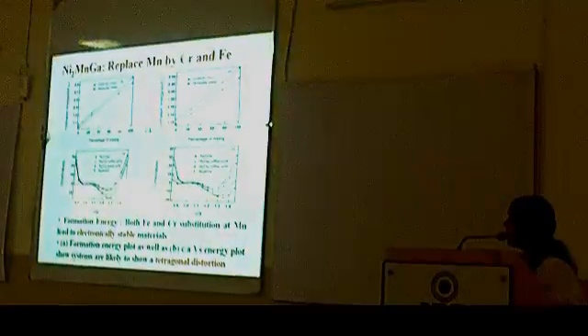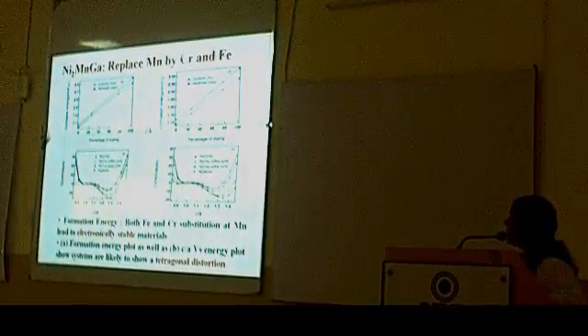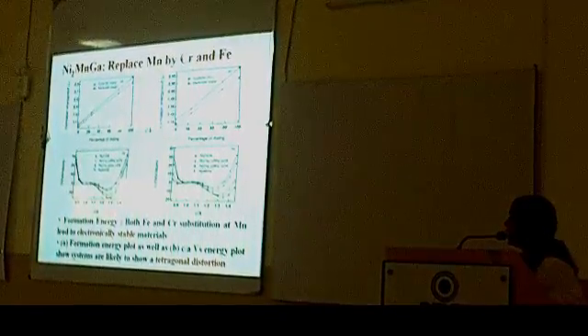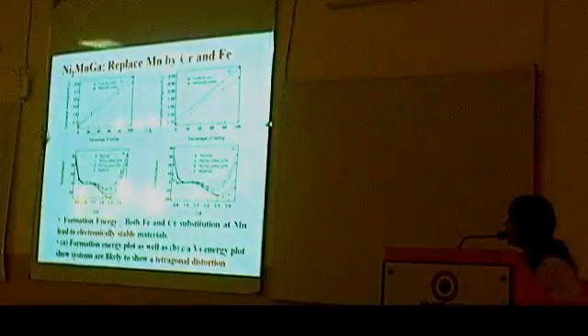This is for Fe substitution, and again we see the austenite formation energy is higher, and martensite formation energy is lower, negative, so this is more stable throughout the substitution. They also show a C by A other than 1, so this also is prone to tetragonal distortion.